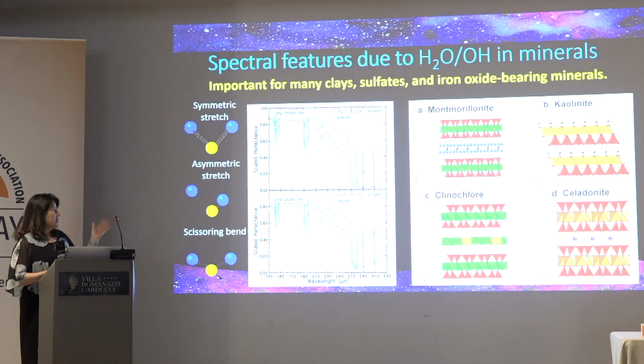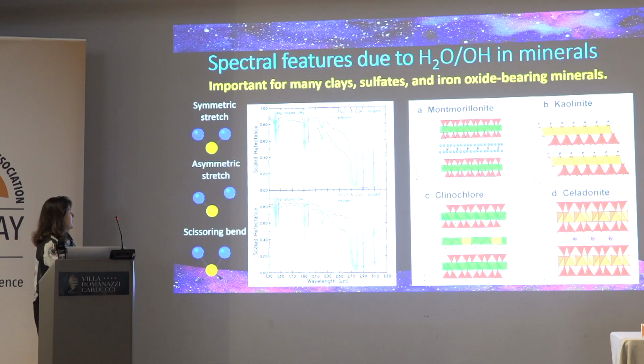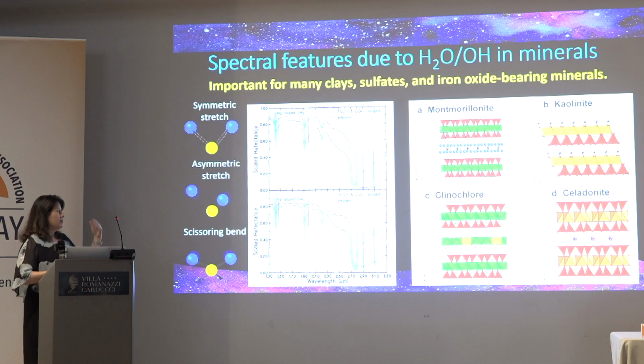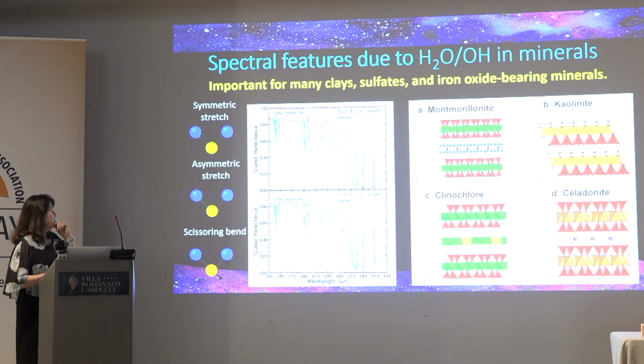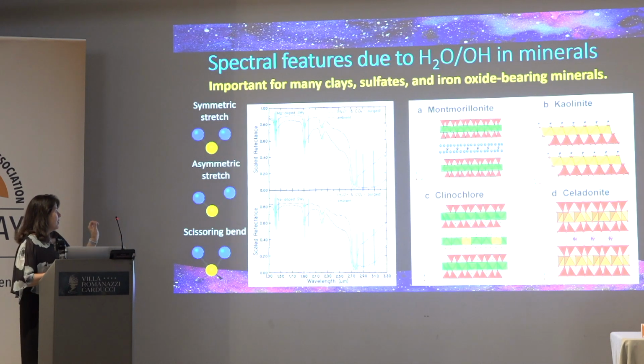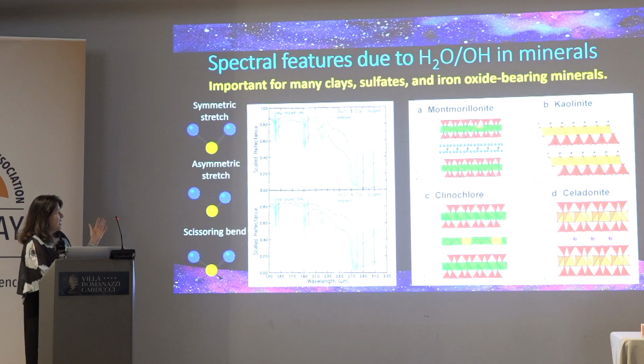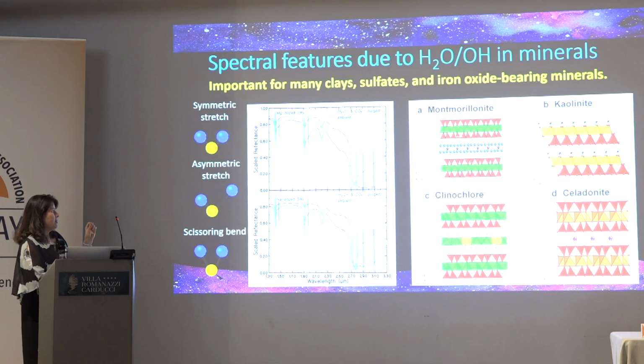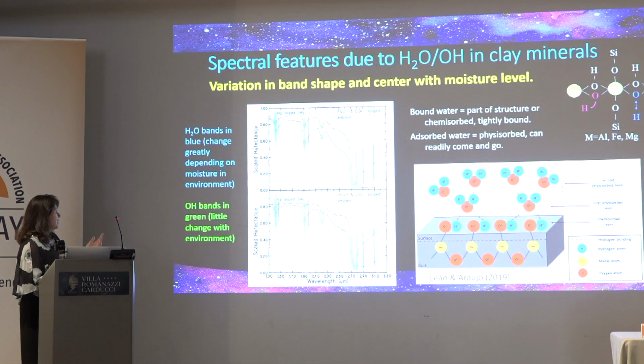And when I was studying spectra of clays back in the 80s and 90s, people were mixing up OH and water, and there wasn't a lot of work on this in near infrared. And so I did a lot of work under different moisture levels to try to figure this out, and especially for smectites, because of the interlayer region, the amount of water depends on the type of cation and how humid it is. And so we were able to use that to help figure this out.